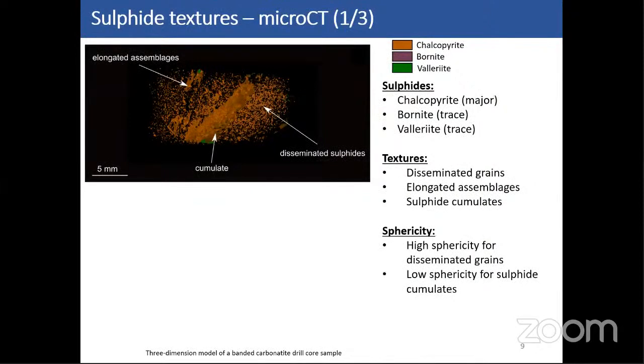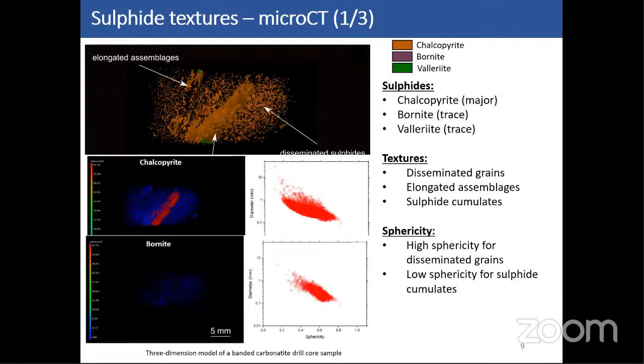Very interesting feature with microCT. First of all, it doesn't show the same results as optical microscopy and mineral liberation analysis at all. And maybe the first thing is that microCT results show the domination of chalcopyrite over bornite in terms of primary sulfides, as you can see on this picture. And maybe it's more clear with these two heat maps, where there is chalcopyrite here, bornite there, so there's a clear domination of chalcopyrite over bornite.